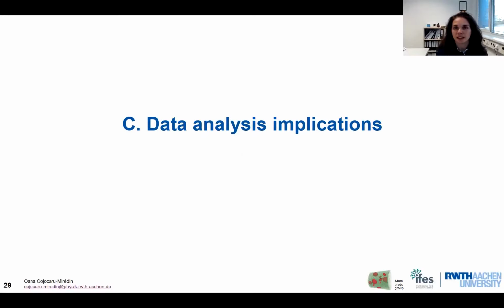So before ending the second part of the lecture, I would like to make some conclusions. I hope it was clear that the field penetration depth is a really important parameter to be explored for molecular ion formation. It is also strongly dependent on the physical parameters of the semiconductor materials like band gap and the dielectric function. There are also other potential effects, and we know that we have in general an inhomogeneous heat distribution inside a tip, and this can explain why we have an inhomogeneous field. So we generate an inhomogeneous shape of our tip, then an inhomogeneous distribution of the field on the apex of the tip, and therefore an inhomogeneous distribution of the molecular ions on the detector. Let's go and speak about the data analysis implications.